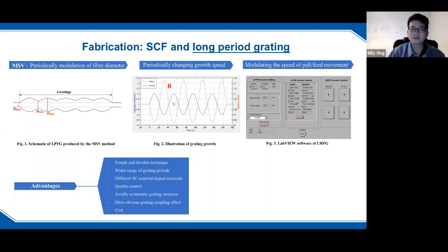So in that precision dicing method, because we grow the fiber with the grating together, we can choose our source rod for the fiber. So we can use different single crystal material and dopant material for the growth of the fiber, and also for the grating, for different applications based on their characteristics. We also find that with this technique the grating response is more sensitive, and lastly it is a cost-effective technique because you grow the fiber and grating together, not only from the raw material, but you can also save money on the grating fabrication and on the commercial sapphire single crystal fiber.